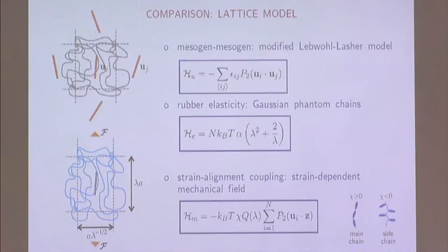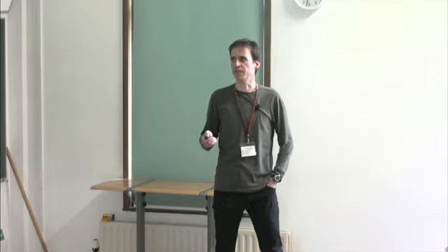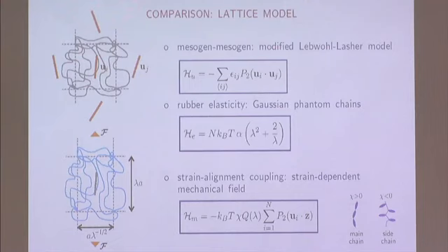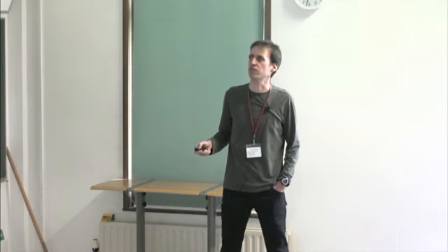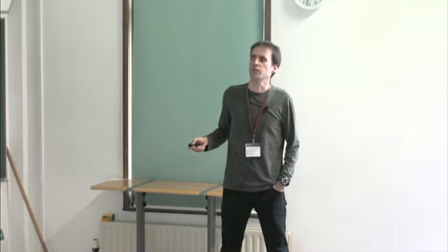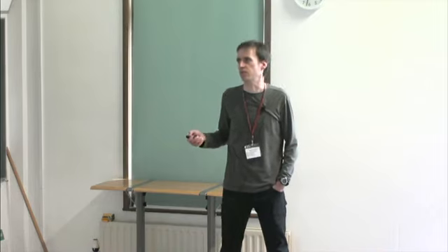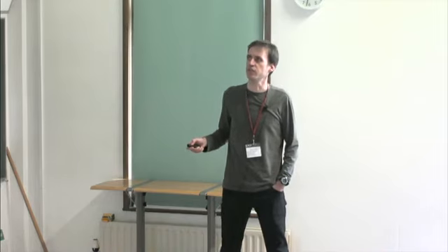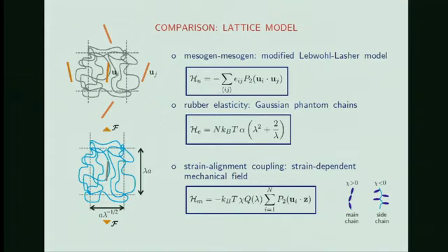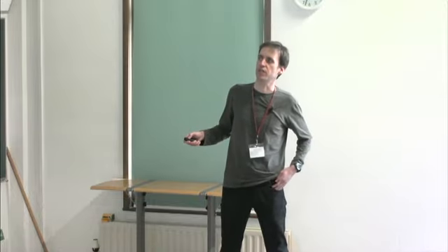But now the most important ingredient, of course, is to couple the strain and alignment. And we decided to proceed in a manner very similar to the Maier-Saupe theory, where each molecule experiences a local aligning field, and the strength of this field is proportional to the degree of ordering of the surrounding nematic material. So again, here we have this P2 term describing the action of a field. The field here is directed along the z-axis, and here we have this Q of lambda, which is what we call the mechanical field strength, and it depends on the actual deformation of our system. If lambda is equal to 1, if there's no deformation, this Q should vanish. There should be no aligning tendency, and it should be positive if we pull on the sample. If we compress the sample, it should be negative, and so on.